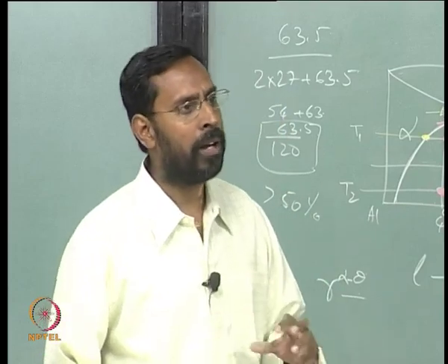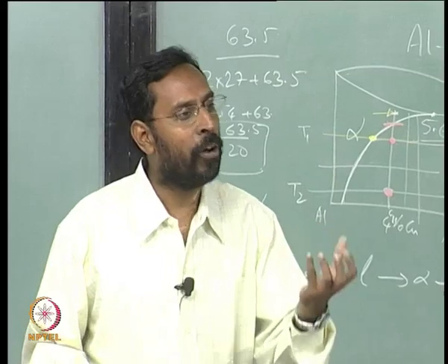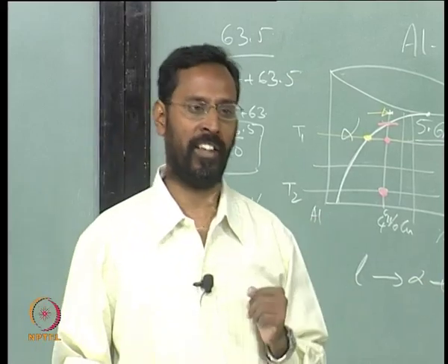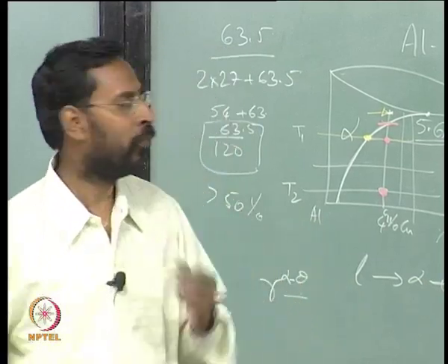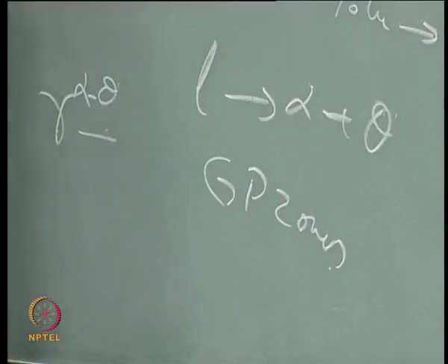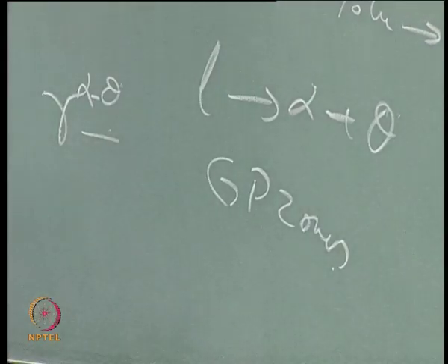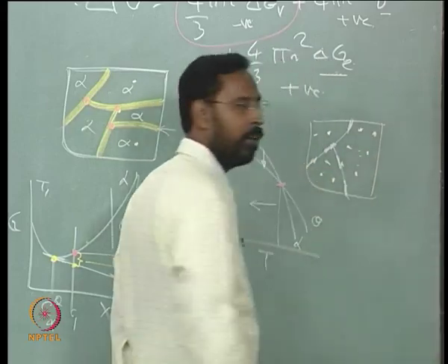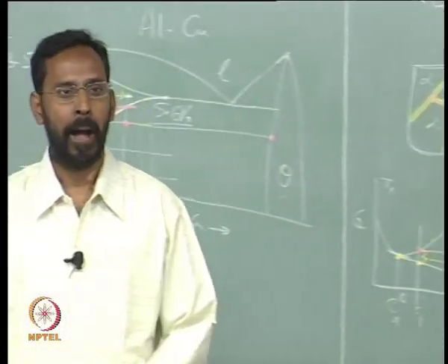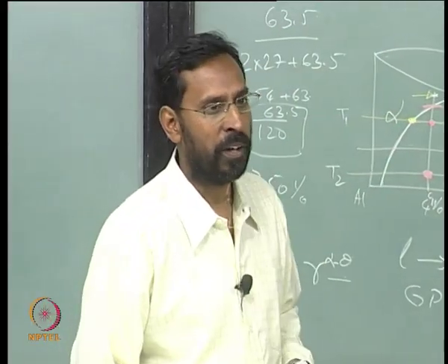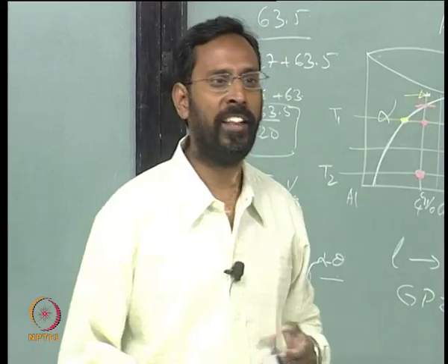Are there any possible transient phases which can have a lower interfacial energy? So it starts looking for transient phases, which are metastable phases of course, but looks for those which have a lower interfacial energy, and that is where you come across something called GP zones. So the alpha precipitates what are called GP zones inside the grains at different regions, and the only heterogeneous nucleating sites here are what? Yes, dislocations. Anything else?